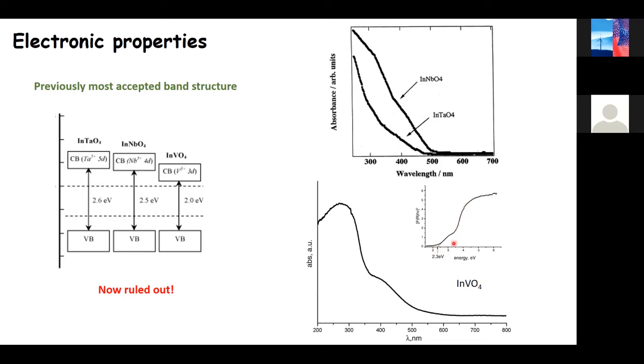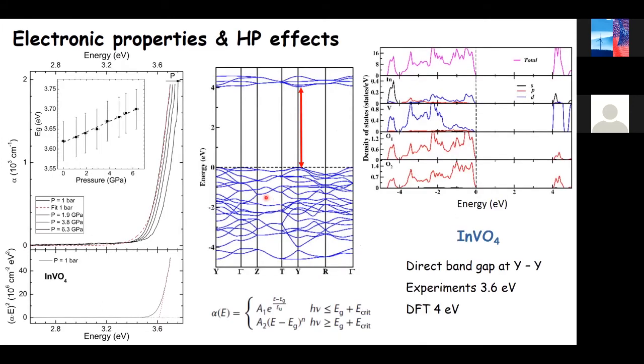which you will see is crossing close to 3.5. And this is just absorption. It's an Urbach tail related to the absorption of defects. This is important. It's not just for your applications. If the band gap is 2.3 or 3.6, it's very different. So we have accurately determined it. So we have done optical absorption experiments.